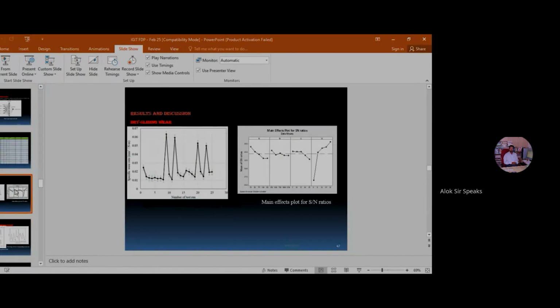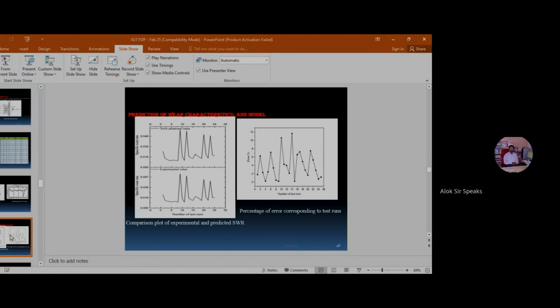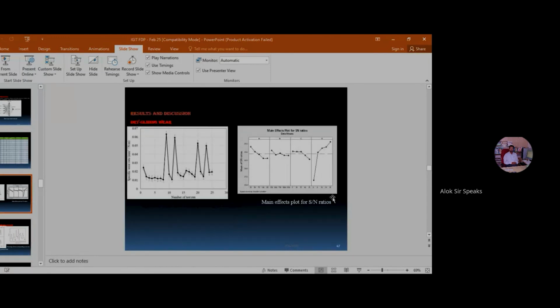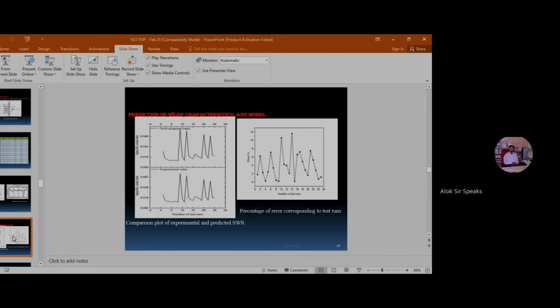Now these are the different sliding wear test results, showing how the sliding wear is varying, and on the right side you can see the main effects plot. The main effects plot tells which of the many factors, sliding distance, sliding velocity, normal load, and filler content, is the most significant one affecting the specific wear rate. You can see that D is the filler content. Filler content is 8%, 16%, 24%, and 32%. These are the different filler contents we have taken in the first place, and we found that the slope of this curve is highest, and therefore this is considered to be the most significant factor which affects the specific wear rate. So wear rate is affected by filler content.